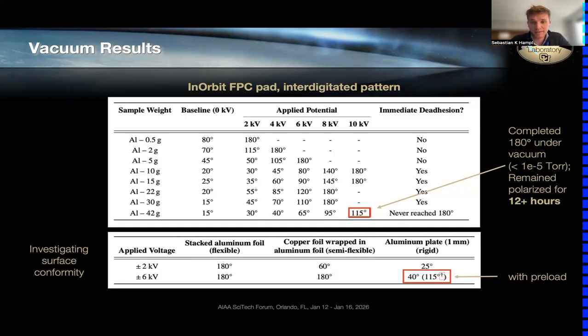There's some variability within this. All of these tests were performed in atmosphere, and this is the atmospheric variability that I was talking about, and also probably related to how well the surface contact between the sample and the electroadhesion pad was in these experiments, which might differ just due to the mechanics of gravitational preloading. If you preload directly by applying a force before, you get much better surface attachment than just from gravitational preloading.